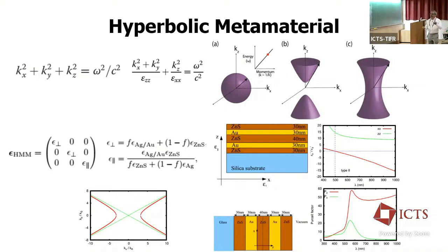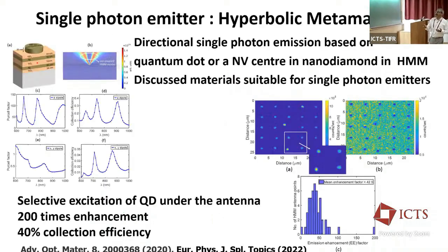So that makes it unique, because if you have a dipole emitter inside this structure, you can effectively couple the emitted photons into this hyperbolic medium. But these modes are evanescent in the far field, so we couple a dipolar emitter and a suitable antenna on the top, so that we can get directional emission from these structures.